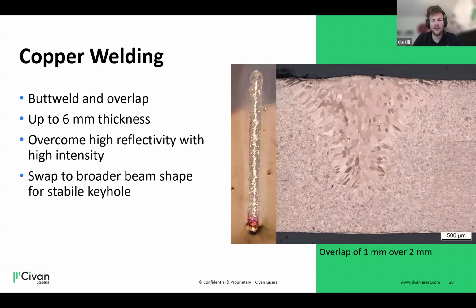Another topic important to the automotive industry is welding of copper. If you have tried copper welding with a laser, you will be familiar with the problem of very high reflectivity of copper. That's why some solutions include green or blue wavelength, which has a higher absorption rate in copper. Some even use two lasers, one in the blue or green regime to create a keyhole, and then a laser in the infrared regime, like the Civan laser, to keep the keyhole open.